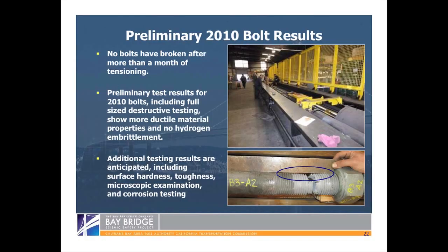The most important finding, of course, is out there in the field on the pier, and that is that none of these bolts have broken. And so the longer they are there not doing that, the more daylight we are seeing between the 2008 bolts, which had a hydrogen embrittlement problem that, generally speaking, develops in the short term, and the 2010 bolts that do not seem to be developing this problem. The preliminary test results as well are showing them to be a more ductile or flexible material, not as hard, especially on the surface, as Malcolm indicated, which was a major culprit in the failure of the 2008 bolts. And we are not seeing any hydrogen embrittlement.